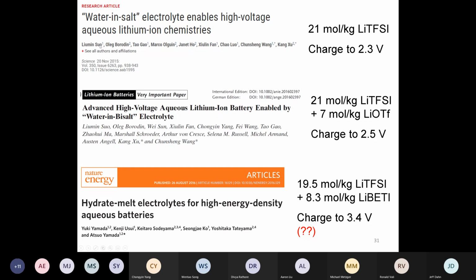The story is he did some high concentration LiTFSI salt in DME electrolyte back during his PhD study for lithium sulfur battery, which works extremely well, especially for the lithium metal anode. So when he came to Maryland, we had this huge ARPA-E aqueous battery program. I think the natural instinct for him was to just try the same salt in the aqueous system. Surprisingly, it even reached 21 molal TFSI concentration. It's molal, which means moles per kg.